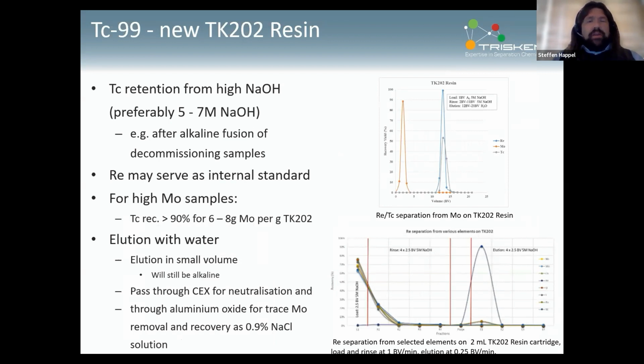So again, retention should be from something like 5, 7 molar sodium hydroxide. One example that we feel is quite interesting, that is currently under beta testing, is work on alkaline fusion. So decommissioning samples, for example, concrete samples that were going through alkaline fusion, taking these, go through the resin, try to retain the technetium, rhenium, which may serve as internal standard. As you can see, in terms of chemistry, it is close enough, it would seem, to allow it to be used as a proxy for the technetium.